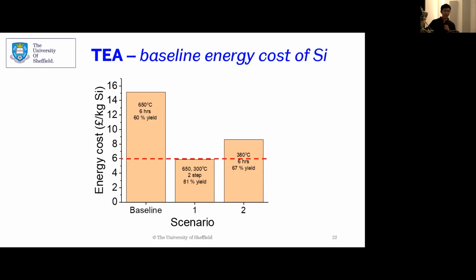Really, it's staying at 300 for most of its time. At 650, it's only there for half an hour. It's a benefit over this method, but it will take longer because in the whole scheme of the process, you have to ramp the temperature up to 650 and then allow it to. So it seems the most obvious option here, but there'll be some scheduling problems that has.